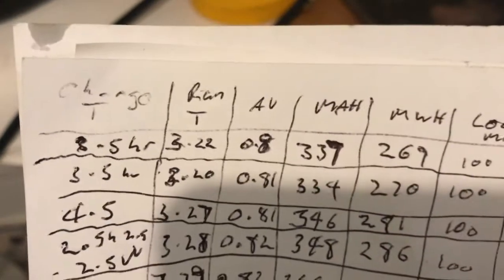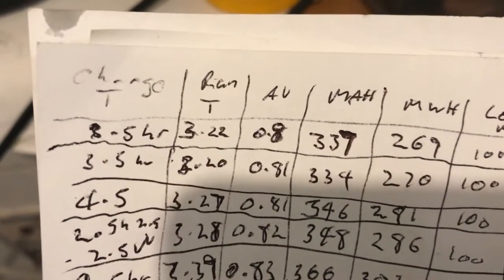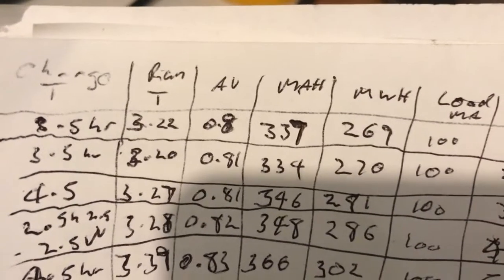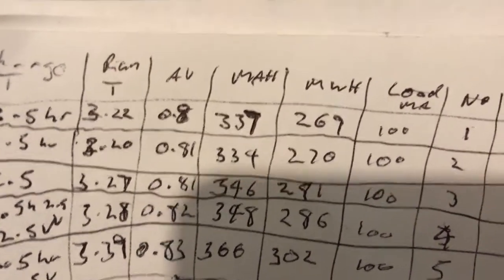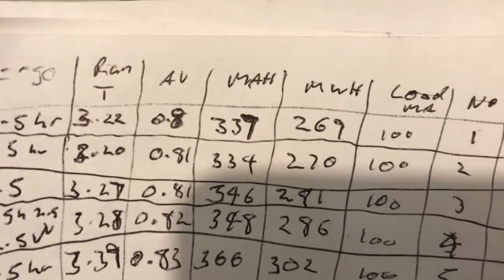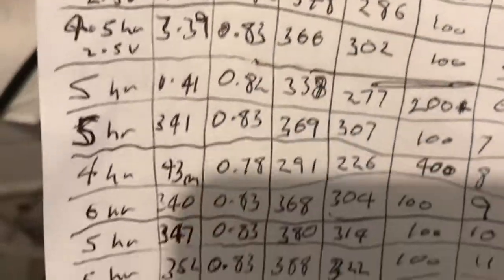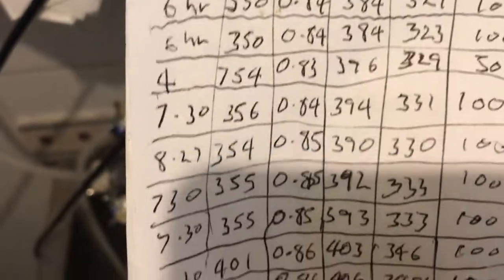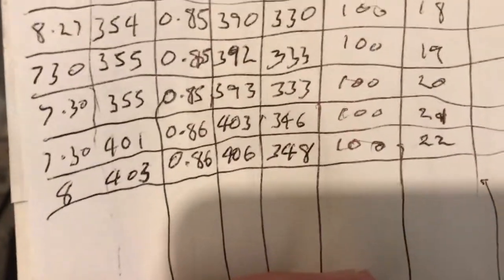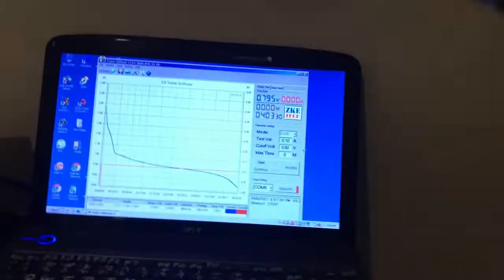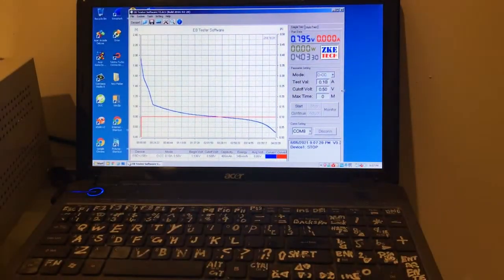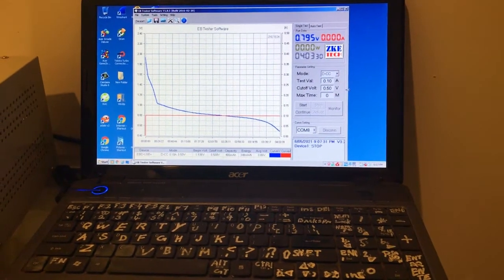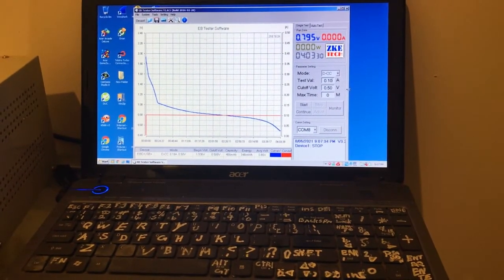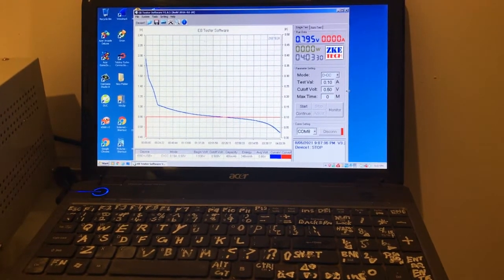It did start off at 2.5 hour charge. We got 3 hours and 22 minutes, average voltage 0.8, and 337 milliamp hours. So the cell's actually increasing, so I'll keep charging. And I'll get back. I want to try to get 100 charges, but that's going to be 100 days time. Well, 80 days now, because we're at 22 charges, one a day.